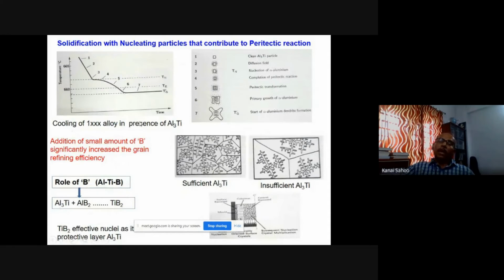I'll take the example of, say, aluminum alloy. We add the aluminum titanium alloy, and in some cases aluminum titanium boron, to do this. Here I showed, see, 660 is the aluminum temperature, but the nucleation temperature is above that. So before solidification of the aluminum, your nucleation starts over here, and that you need to get a very fine grained structure. Okay, so it is sufficient amount of Al3Ti, sufficient amount of aluminum titanium boron, you have to add. Boron intentionally we add, so that a lot of TiB2 particles are there, so that they can act as effective nuclei to protect the layer of Al3Ti.